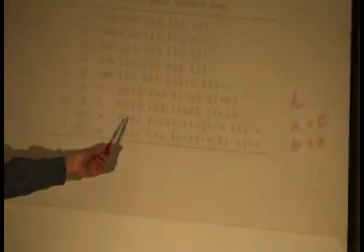Don't start to be scared. What position did we start working with? That one, right? It's a special position, okay? So, our y coordinate is not y. Our y coordinate is 0, okay?